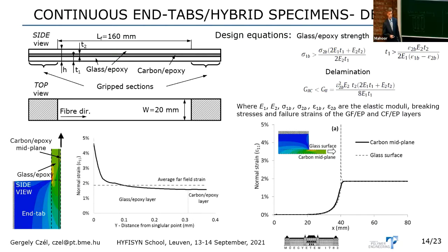These are actually numerical models to prove that we do not have stress concentrations at all in the carbon layer if we use the glass epoxy layers on top of them. And why is this? It's because we have a very strong stress concentration, but in the glass layer, which has a higher failure strain, so it will not fail at loads or strains we want the carbon fiber to fail. So we overload the glass, but it can take it, no problem. On the other hand, the carbon layer, which is between the dashed and the solid line, doesn't have any stress concentrations.